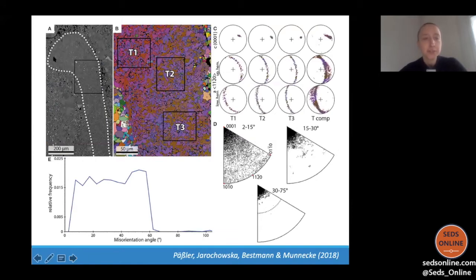This is a trilobite fragment in the backscatter image. And you can see already from the colors that the orientations are very constrained, and that's visible in the pole figures where all the C axes are very narrowly clustered in one place. And the rotation around the C-axis is also extremely well constrained. And voila, we can see that the misorientation axes are also extremely well constrained. So this would be our reference for biologically controlled biominerals.